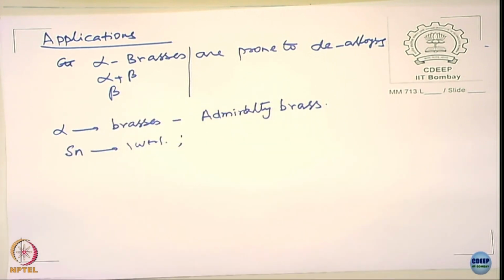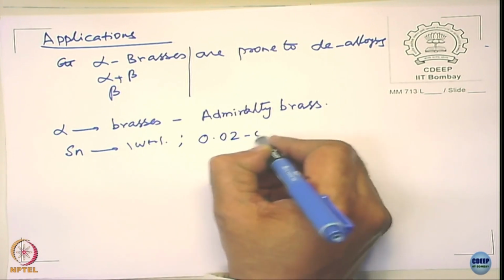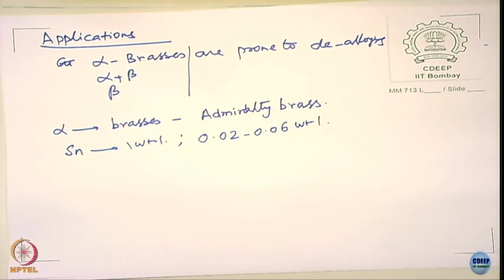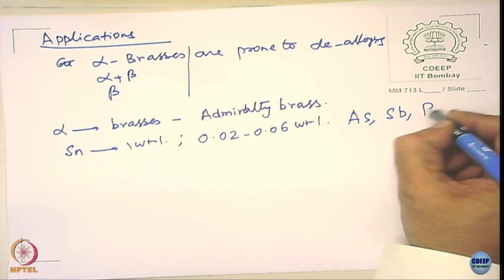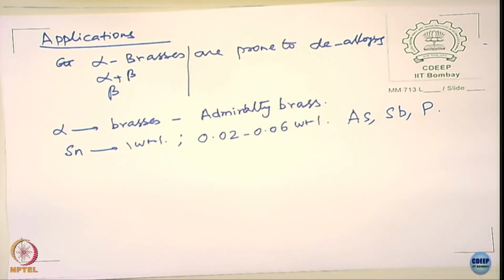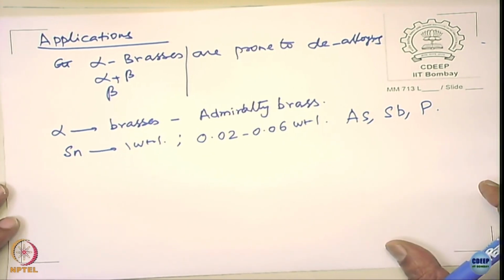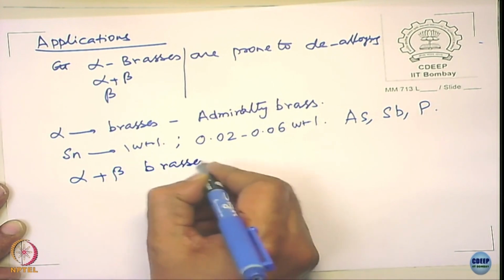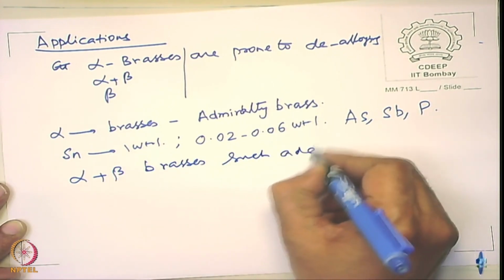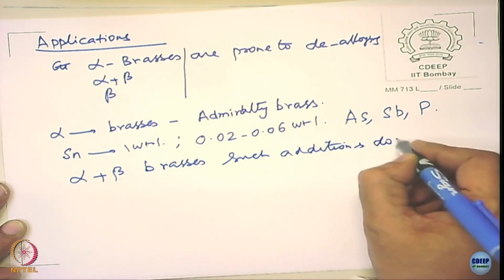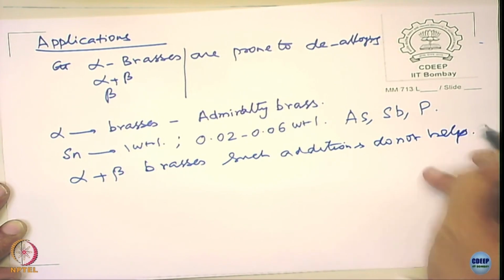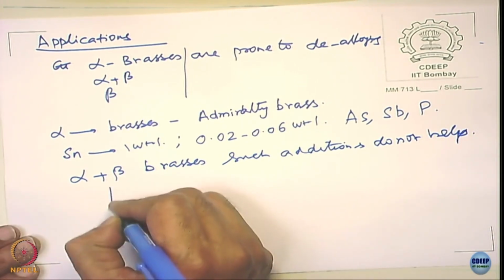To support this, they also add small quantities, weight% of arsenic, antimony and phosphorus, and they are effective in curbing the dealloying of alpha brasses. The mechanism is not completely known, okay. There are some speculations, but not completely known. But for alpha beta brasses, such additions do not help. So, they continue to undergo dealloying, same as the beta also, right.